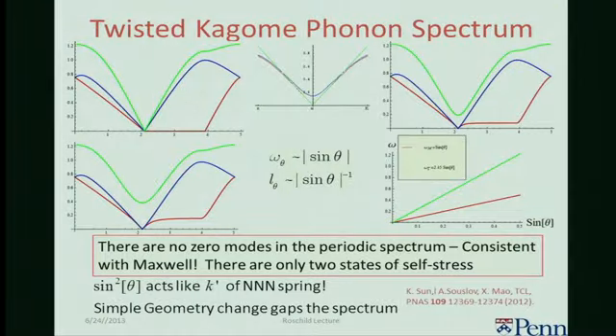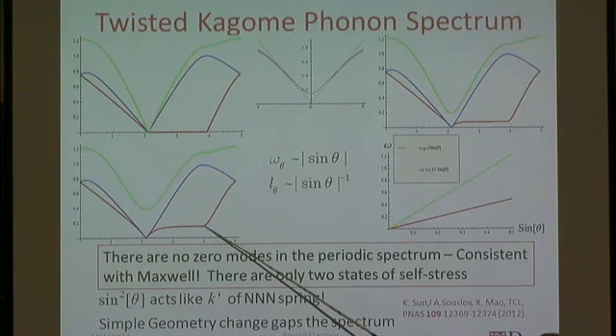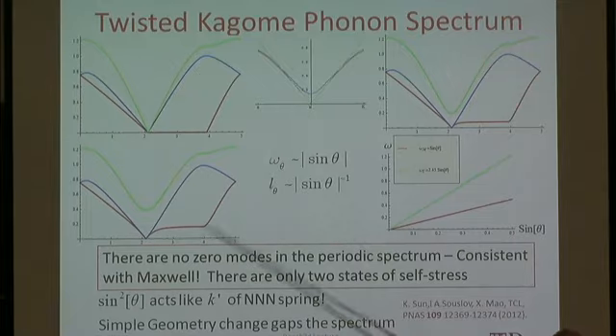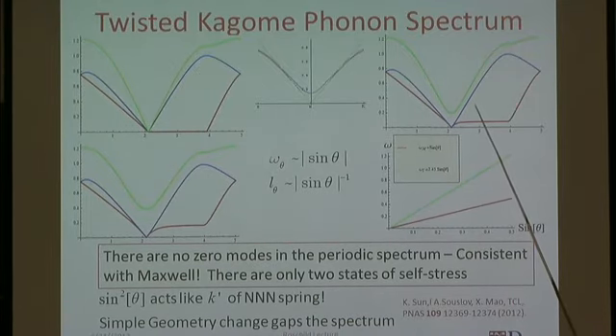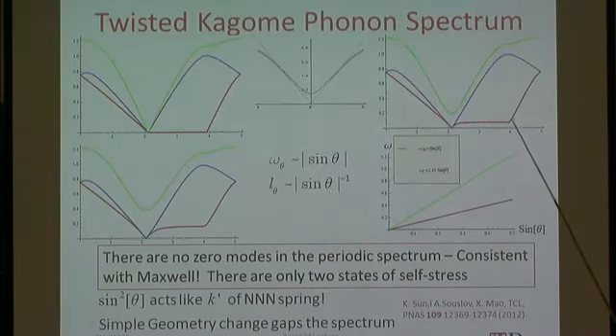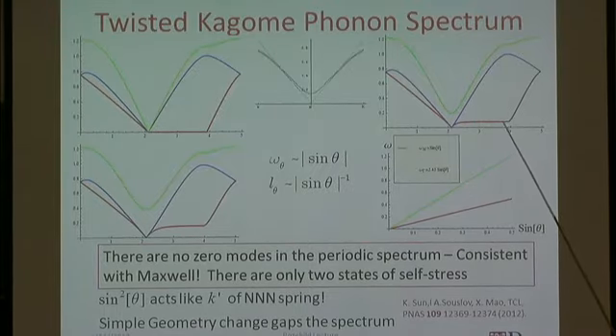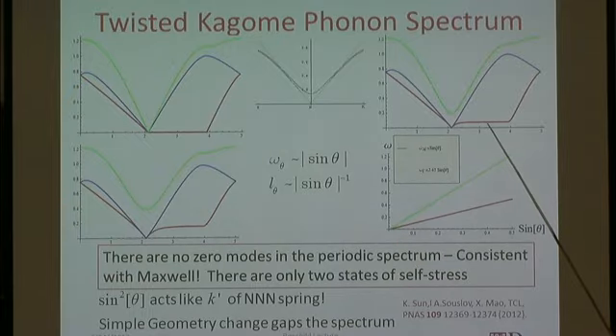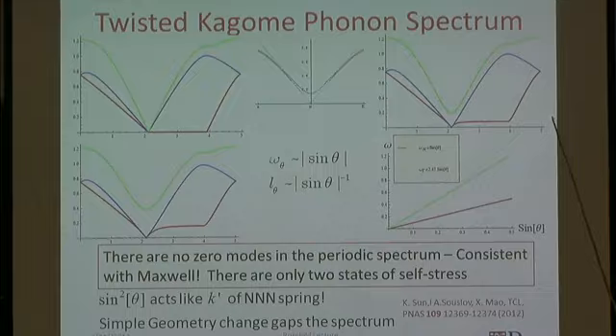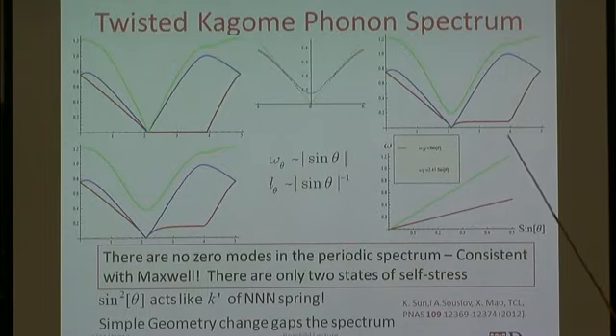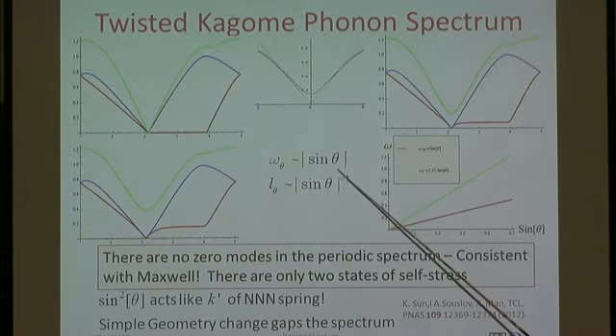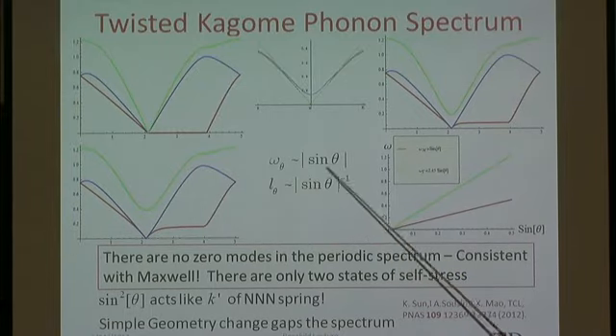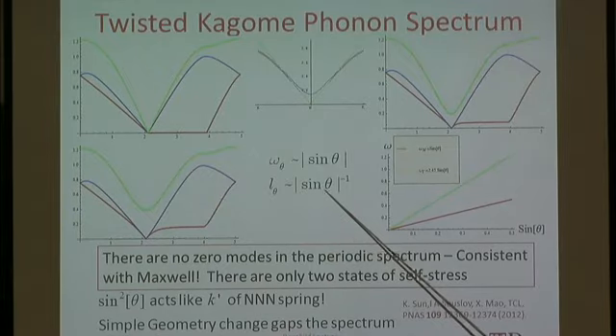Now let's go to the spectrum of the twisted lattice. If I don't twist the lattice, I've got this spectrum where we have a zero mode running from gamma to m. I add next nearest neighbor forces, we get a gap, which is proportional to k prime. I twist the lattice, we get a gap without doing anything. I haven't added any next nearest neighbors. All I've done is to go from the untwisted Kagome lattice to the one where it's twisted, and I get a gapped spectrum with a characteristic angle, which should have been omega going as sine of theta, and a length that goes as 1 over sine of theta.